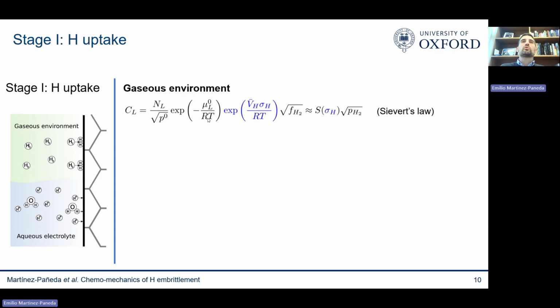But again, this is good news because I can measure the stress-free solubility. This term comes from a finite element analysis for whatever defect I have, and this comes from the environment, so I can predict my hydrogen concentration.